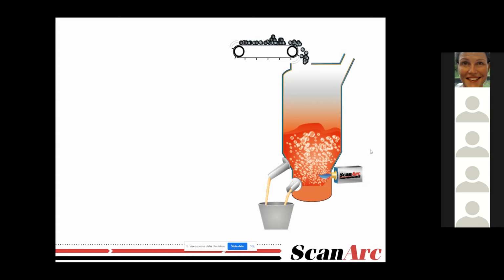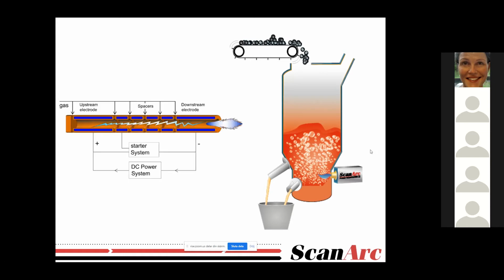What you see down below the box at the right bottom part of the reactor is a plasma generator, and that is a way to convert electric energy to an extremely hot gas. Inside the reactor, we use electricity, as said. Inside this reactor, a plasma flash is generated, and we inject gas, which is then heated up by this plasma flash and flows through the plasma generator and goes into the molten bath under a very high flow rate. The gas that leaves the plasma generator has a temperature of up to 5,000 degrees. So it's a lot of energy in a quite small amount of gas volume. As said, this is a way to create a hot gas from air and electricity without involving combustion reactions or fossil fuels. And then, of course, best case would be if the electricity would come from a sustainable source and not carbon.